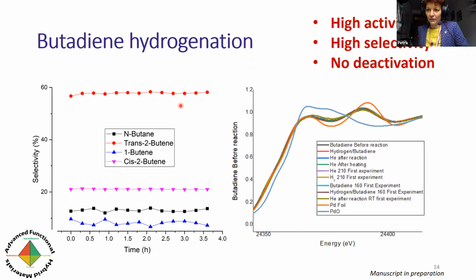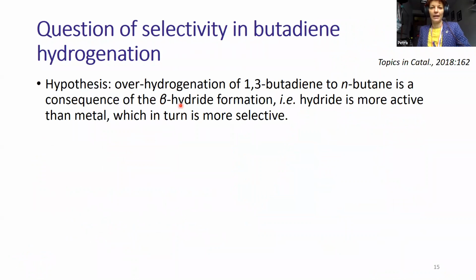We also carried out some extended X-ray absorption fine structure analysis in operando conditions. And that told us that there is no obvious change of oxidation state of the palladium in the course of the reaction. But of course, this is not necessarily the best method to determine whether or not a hydride phase is formed. However, what we can tell is that there are no oxides formed or such things, and it seems that it's fairly stable from a chemical viewpoint as well.